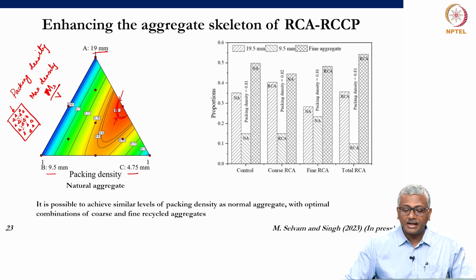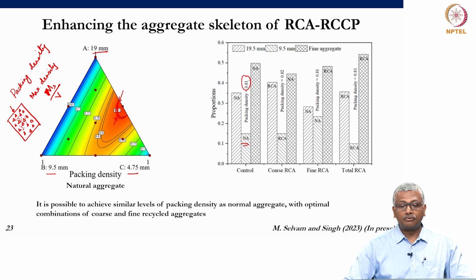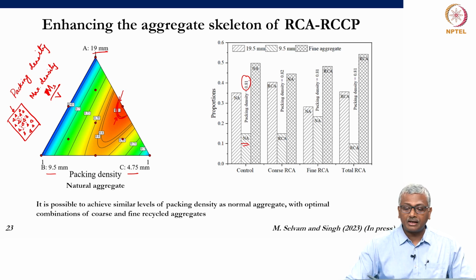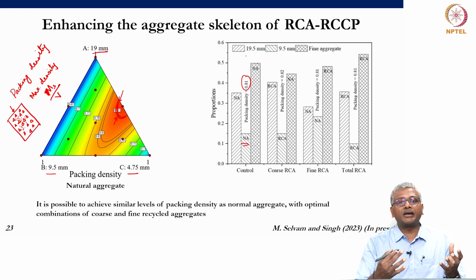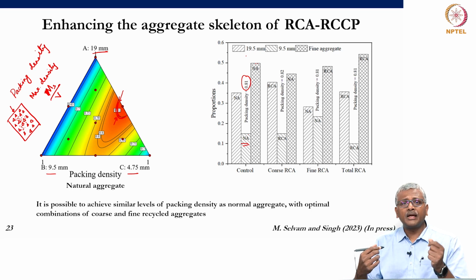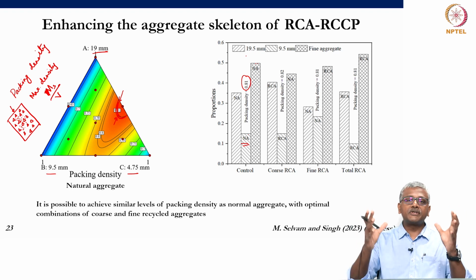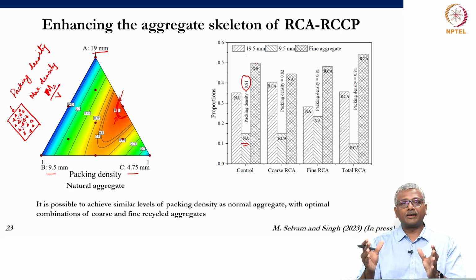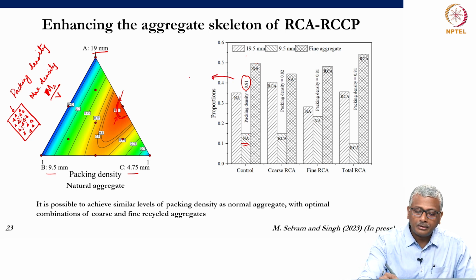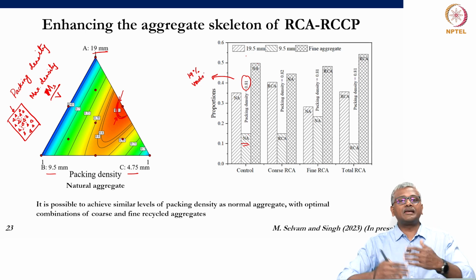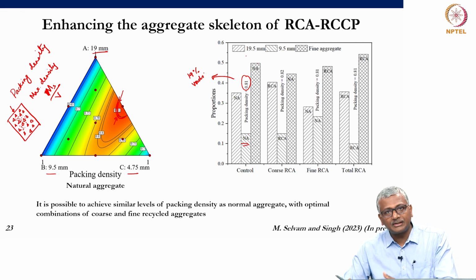So, what is done in this study is that for normal aggregate, right, packing density obtained was 0.81 for an optimal choice of fine aggregate and coarse aggregate. For instance, here it was 19.5 millimeter aggregate was about 35%, 9.5 aggregate was 15%, and the fine aggregate was about 50%. At this level, they got an optimal packing density of 0.81. That means, if you take a volume of container, 81% of the volume is filled up by solids of the aggregate, or you get 19% voids in the system, okay. So, you can think about maximizing packing density as also the same function as minimizing the void fraction, okay.